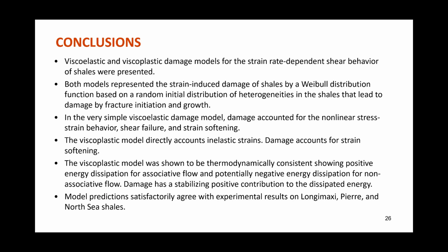So increased fracture length means increased damage area or reduced load. In the very simple viscoelastic model, damage accounted for the nonlinear stress strain behavior, shear failure, and strain softening. All of them are accounted for by the model. A failure surface was not needed. It's not necessary a priori, but it's simply a consequence of the damage.